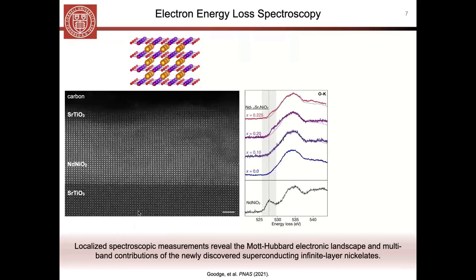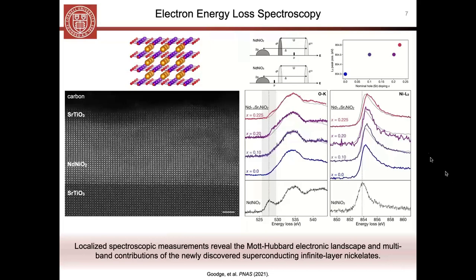And so using very localized EELS in the STEM, we were able to study, for instance, the oxygen K edge, and by comparing the parent perovskite state to the infinite layer state, we can extract the electronic character and reveal that these materials are unique from others and that they're actually Mott-Hubbard materials, if people care what that is. And we can also look at the nickel edge, which is particularly compelling with EELS, to be able to compare both edges at once. Because now, being able to study the two correlatively, we can show that there are some really intriguing multi-band contributions apparently happening in these materials, again, unique to other superconductors in the past. So that's just a really quick overview.